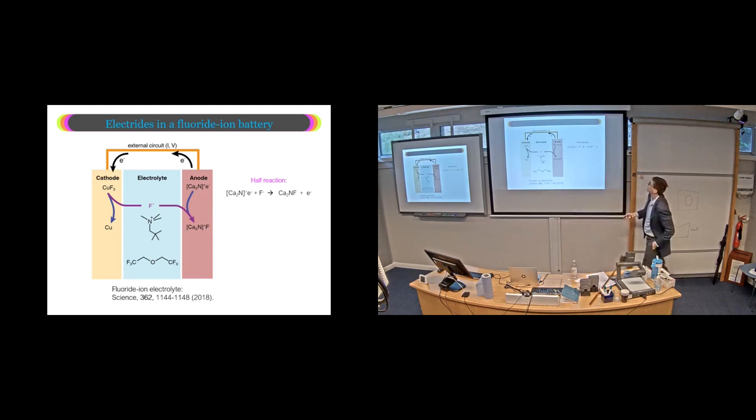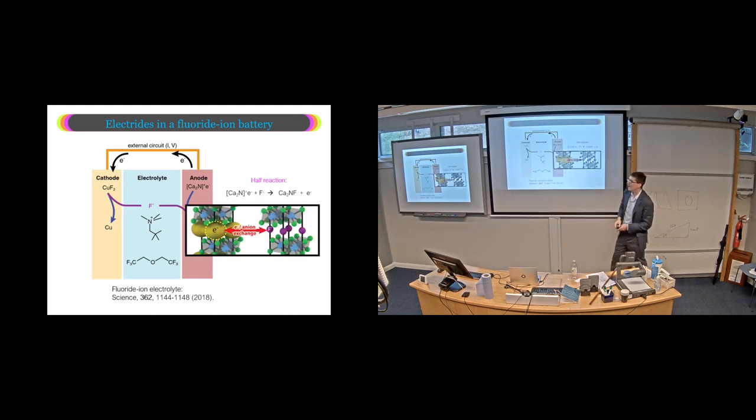So we would get this electrolyte from Honda and started to do some testing of this intercalation process in our lab. The overall picture here is we've got a cathode like copper fluoride getting converted to copper that releases fluoride. Fluoride comes across the electrolyte and intercalates into the calcium nitride. The electron is replaced by a fluoride. That electron leaves and goes out through an external circuit, completing the circuit. So this, in some ways, has the same kind of flow diagram as a typical battery, where you have ions moving through the electrolyte and electrons moving through the external circuit. The key difference is that you actually have the electron being lost, not from an atom, but from an interstitial space. One of these electride electrons. So we can write a half reaction that looks like this.